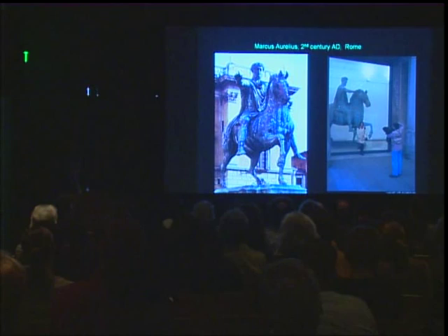In some cases, maybe, but not when one observes that Moore's later bronzes all left the foundry with a lacquer coating designed specifically to resist the corroding effects of outdoor display and preserve the inner and outer contrasts of his distinctive light and dark brown patinas. By the way, the Marcus Aurelius, which was taken indoors for conservation, is now kept indoors, and a replica is in its place in the Campidoglio.